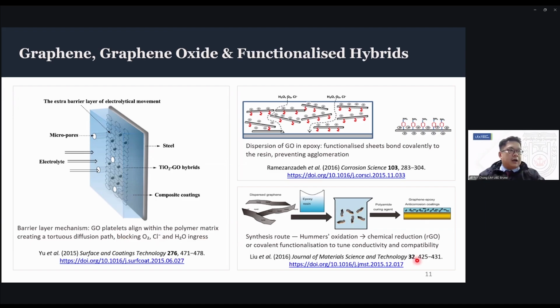But soon after that, efforts to integrate graphene or graphene oxide into organic coatings, such as epoxy, started, and we first see them reported in 2015. When these early efforts were reported, they normally tried to functionalize the graphene. The reason for that is because they wanted to ensure there's good dispersibility and also adhesion of the graphene inside the coating or to the mild steel. So this is on the left.